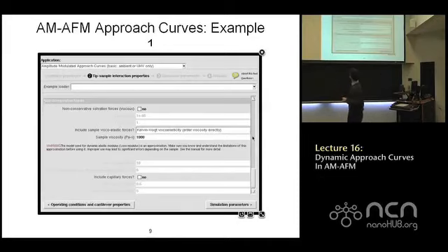What we do is we add a viscoelastic component of the interaction, and that's modeled by a Kelvin-Voigt interaction. So if you scroll down to the portion of the panel which talks about non-conservative forces, you can include a viscoelastic force modeled by Kelvin-Voigt, and enter in a pretty big value of 1,000 here. Also scroll up on that page and make sure the Young's modulus is unity. It's one GPa. I don't remember the default value for that.